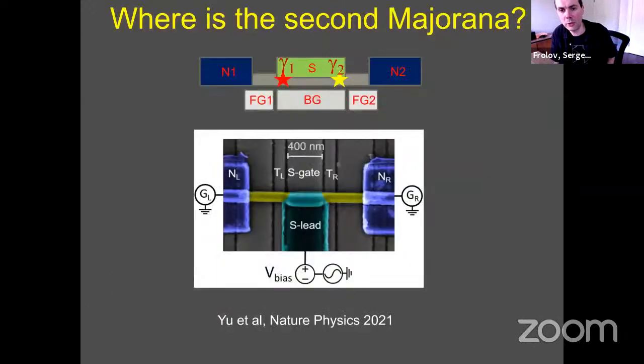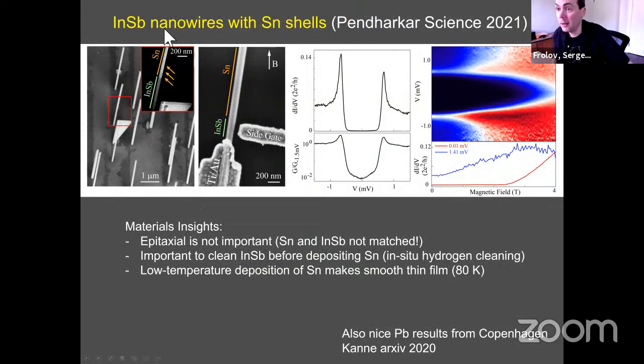Okay, so now let's look at the new signal. Well, so this is hard gap. Here we have the two peaks I talked about, the BCS peaks. And in the middle, there is nothing. This is how it looks on a logarithmic scale. So the background is rather small, a factor of 100 below the peaks. And okay, I mean, it varies when you change gates and so on. And okay, now I can actually get to Carlos's question, which was that he finds it surprising that without requirements of epitaxy, this is possible. I am not surprised. Actually, those aluminum devices also have grains, also have disorder, and still this works.